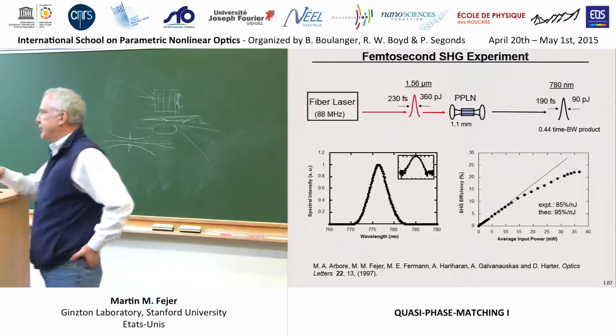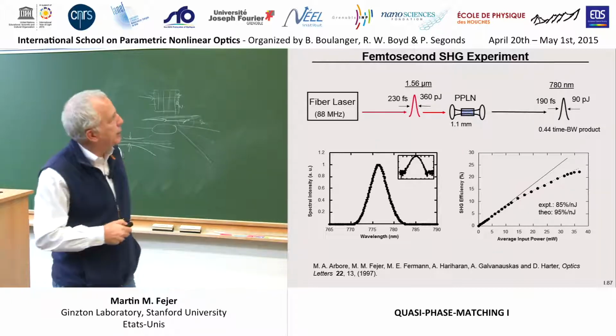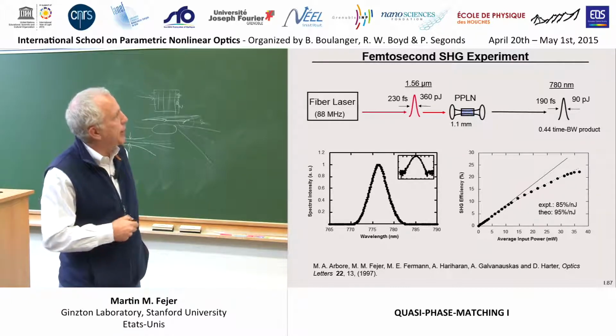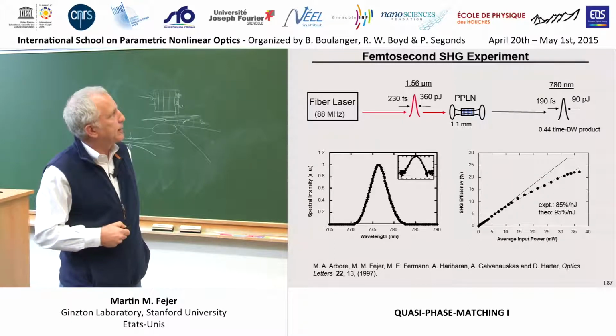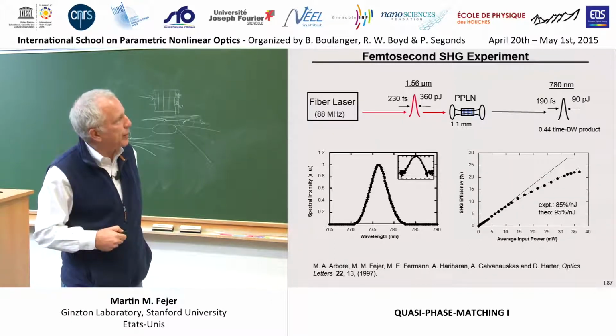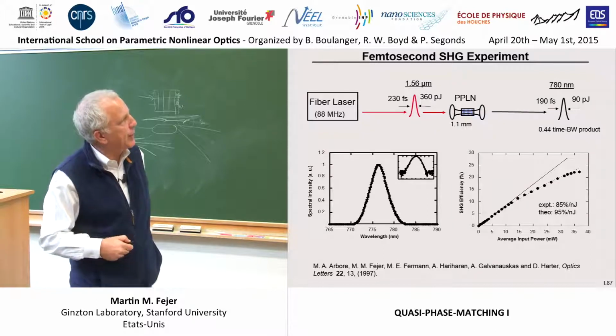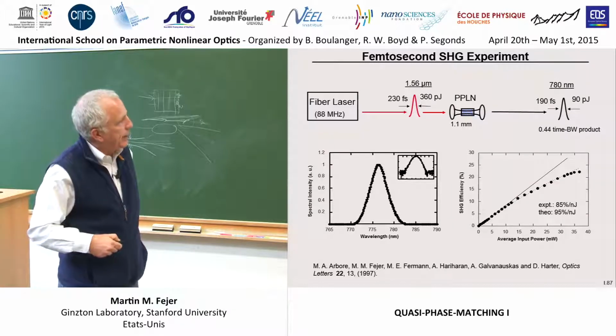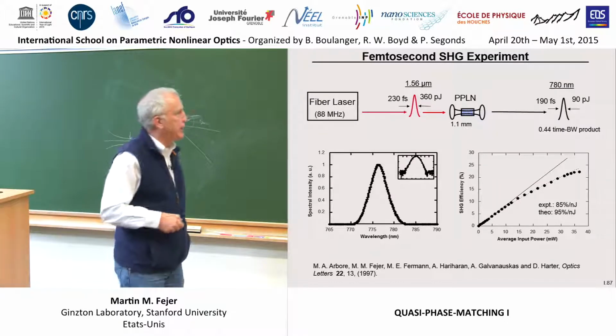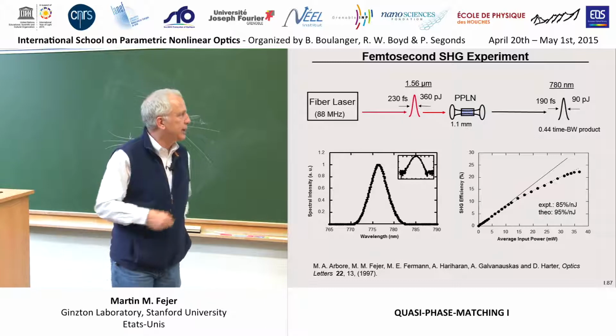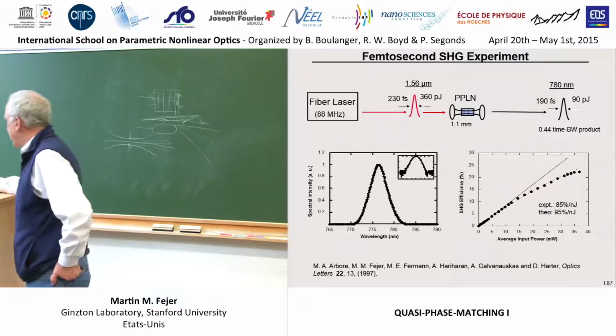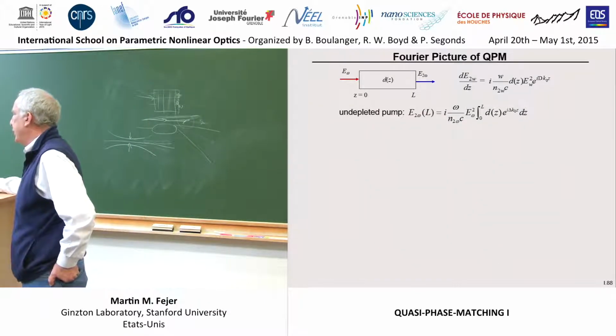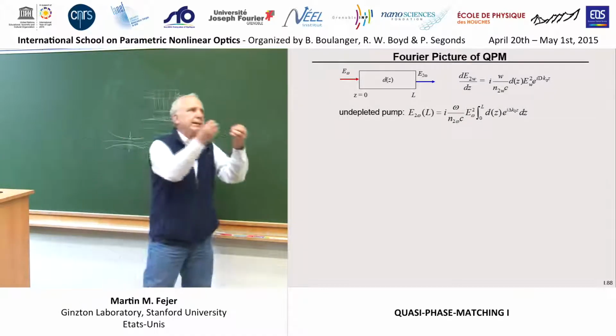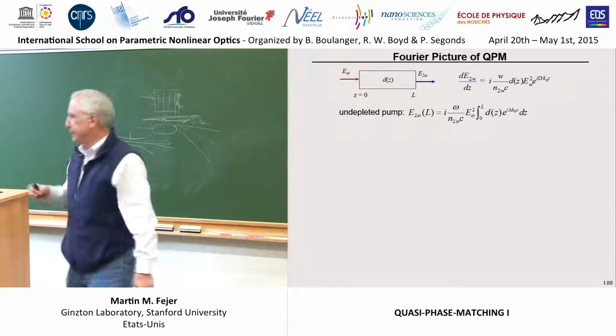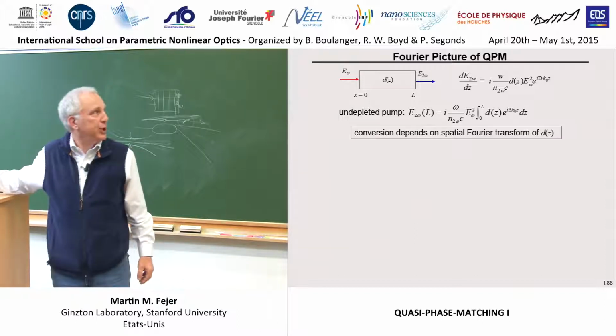And you can do such an experiment. We did this quite a while ago with the IMRA guys, just took one of their simple low-power fiber lasers, couple hundred femtosecond pulse, doubled it in a suitably chosen length of lithium niobate in a single pass, and sure enough, the efficiency looks just about like the 90% per nanojoule that you would have expected, and you preserve the pulse duration as you would have expected. So that simple kind of argument works. So let's now tie that to our Fourier picture of how quasi-phase matching behaves.